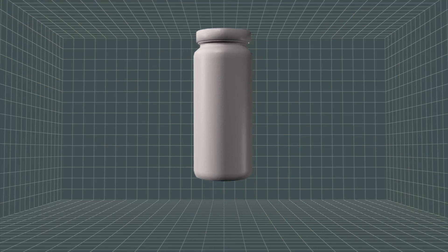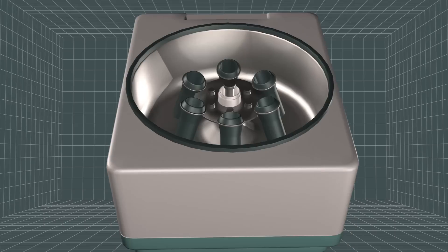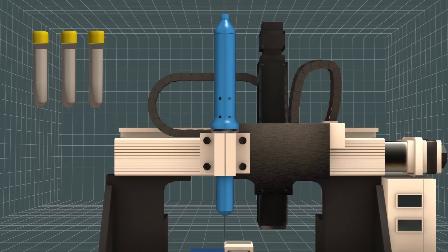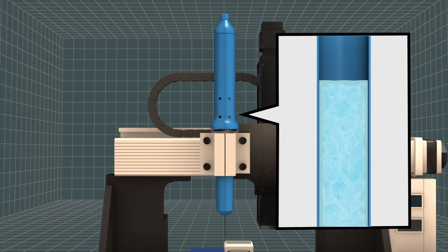The balls and larger particles are removed with filters and a centrifuge. The resulting ink is placed in a syringe and inserted into a high-pressure dispenser on a 3D printer. The ink is solid when unperturbed, but flows under high pressure.